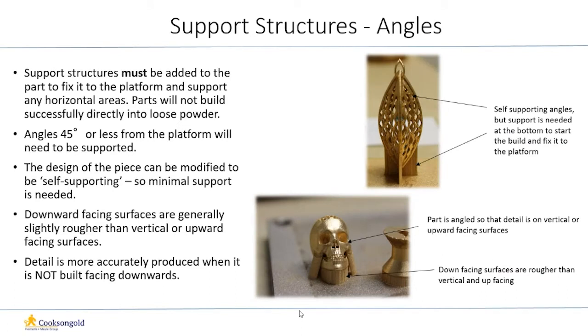Once the part has been designed on CAD, we then use a software called Materialise Magics to generate the supports. Support structures must be added to the part to fix it to the platform and to support any horizontal areas. Parts will not build successfully directly into loose powder. Angles 45 degrees or less from the platform will need to be supported.